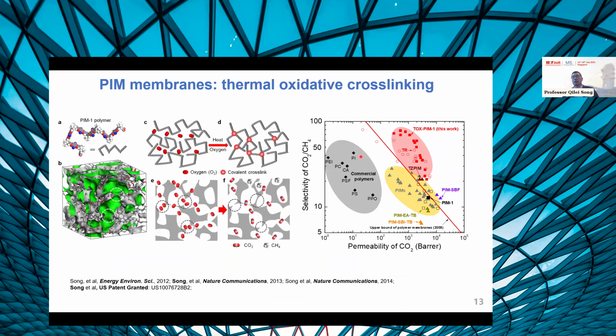So I want to give a brief summary of the work we have been doing on separation membranes using these PIM materials. One of the works I did during my PhD was that we developed a thermal cross-linking method to cross-link the PIM polymers with trace ppm-level oxygen at intermediate temperature, at around 300 to 400 degrees. So we were able to cross-link the PIMs and enhance the selectivity. You can see that the CO2/methane selectivity can be enhanced from a relatively low level, around 10, to much higher selectivity, around 50 or 60. So the permeability didn't decrease much.